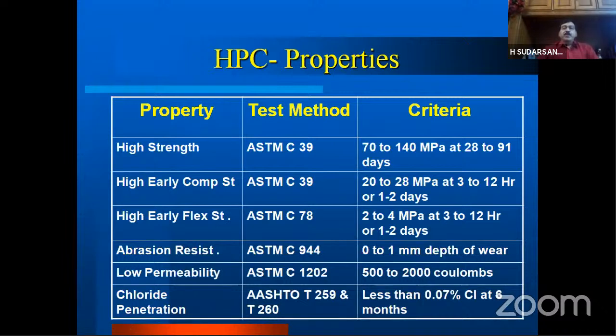So from the different codal provisions, for the different types of properties of the high performance concrete, the criteria I have listed out here. If you say high strength is the property, then as per ASTM C39, it is 70 to 140 megapascals at 28 days to 91 days. High early compressive strength is 20 to 28 megapascals at 3 to 12 hours. You can see how early it is.